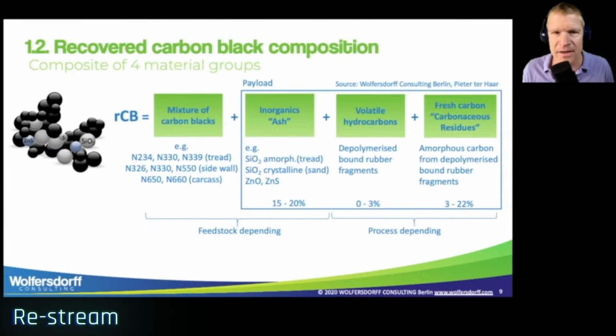So what is recovered carbon black? It's important to know recovered carbon black is a composite of 4 material groups. Of course, we are recovering a mixture of the carbon blacks. There we have to see that tires consist of several carbon blacks. Tires are built up of between 10 and 14 sections. Each section contains its own carbon blacks and its own rubber polymers and additives. So we might recover 200 and 300 type of carbon blacks from the tread. We might recover 300 and 500 types of carbon blacks from the sidewall, 600 and other semi-reinforcing carbon blacks from the carcass. This is, of course, what we want to recover, and it's important to say feedstock control is very important to the quality of recovered carbon black.